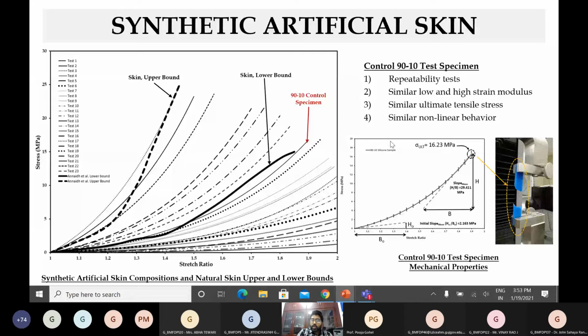Number two is similar low and high strain modulus. So this is a term which we need to understand here. Like I've said, this is a highly nonlinear material, so you cannot have a single modulus or a linear property define this material property. So what we could still do, and a lot of papers and literature have done that, is we create a lower modulus and we create a higher modulus. We draw a tangential line from the topmost point and one from the bottommost point, and we take the slope of that. So we compare that with literature.